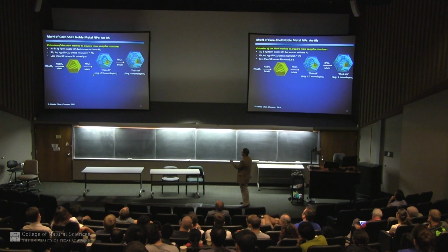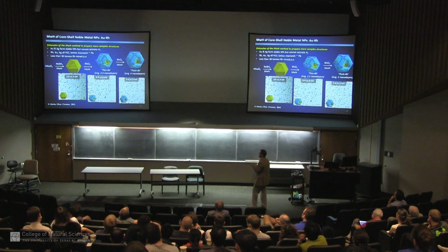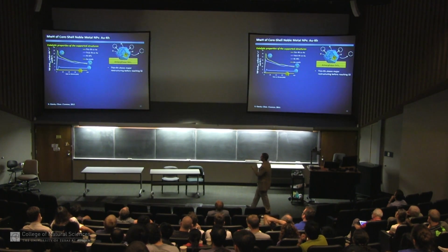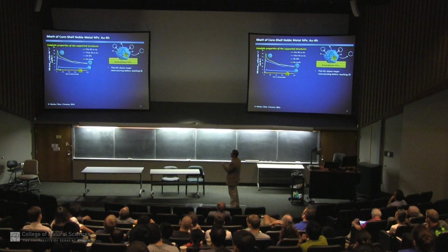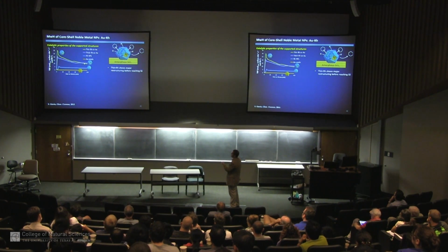So we can assess this by making thin overlays. You can see the particles just get bigger as you grow them. And we saw, to our delight, that these are very active catalysts. This is the hydrogenation activity of gold cores as a test. They're dead. This is the hydrogenation activity of rhodium particles, and these are our rhodium core shells with gold in the core. So you can see they're much more catalytically active.